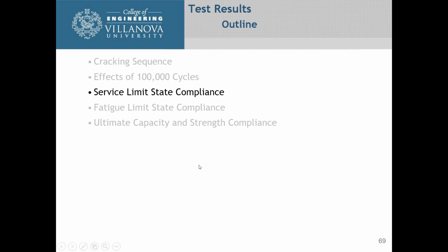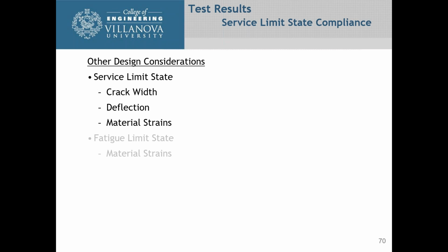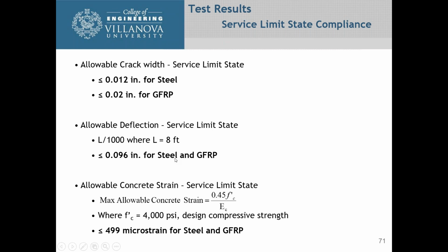So now that we've got all this test information, we want to talk about how this relates to service limit state compliance, and then fatigue and ultimate. So first we're going to look at the service limit state compliance. You have to look at crack width, deflection, and material strains. So the allowable crack width under service from AASHTO and from ACI is that for steel, your allowable crack width has to be less than 0.012 for steel and 0.02 for GFRP.